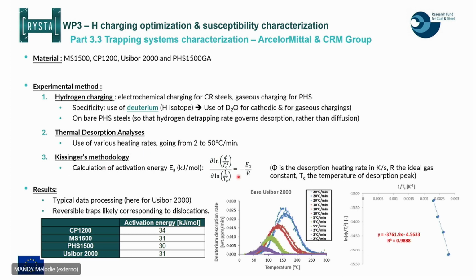So basically, the idea is that when you have a graph like this for one given material with different heating rates, you have a peak temperature which is different at each heating rate. You use this temperature that you put in this equation, and you will find the activation energy that we found here for the material. So as you can see, we have activation energies for detrapping of hydrogen, which are quite close. And here we are convinced that it is corresponding to reversible traps that are likely dislocations for those materials.